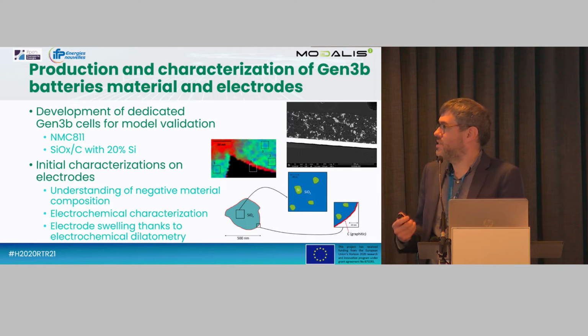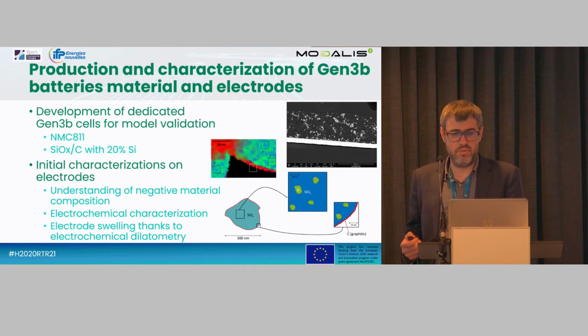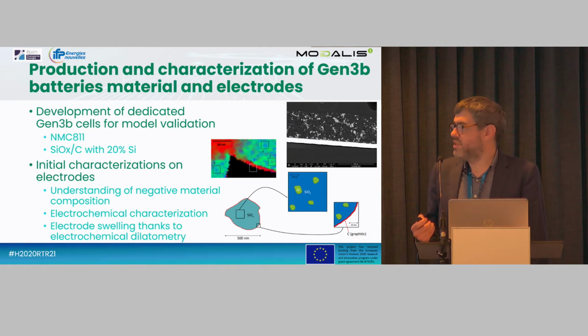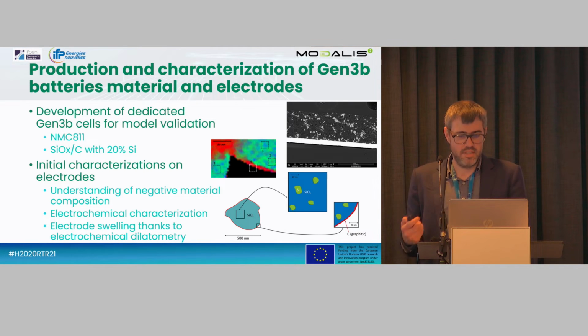So the main achievement that we had in this project is dedicated for the moment to generation 3B batteries, where we have been working up until now. So first, we have developed specific materials and batteries, electrodes and batteries based on the materials that have been chosen. So we chose NMC 811 from Umicore as a positive material, and a blend electrode, a composite material with silicon oxide and graphite at the negative. So we had 20% of silicon included into this material, and this is important because with this amount of silicon, we can see the impact on the mechanical behavior of the composite through the lifetime of the battery. And it has a lot of impact also in the manufacturing phase and the issue with cycling that we can see from the first cycle of the battery.